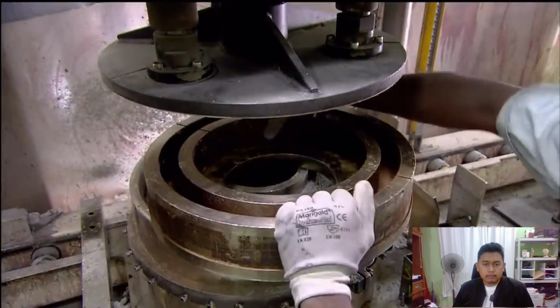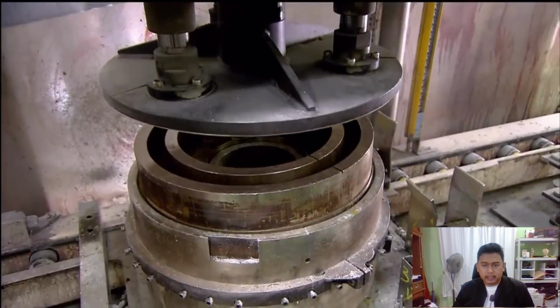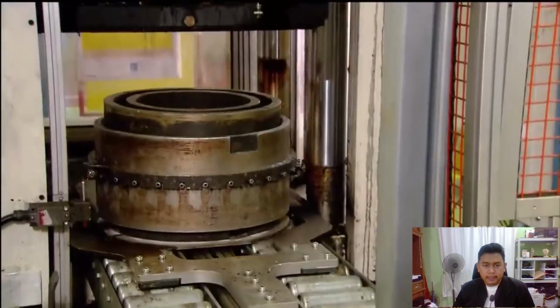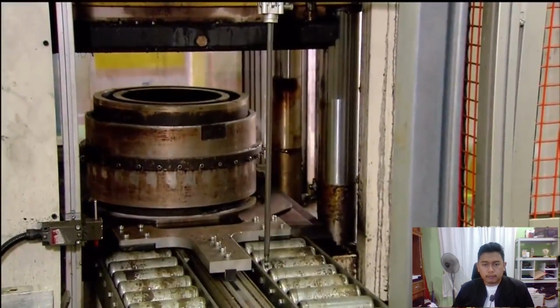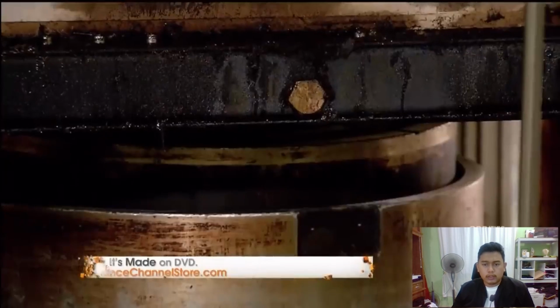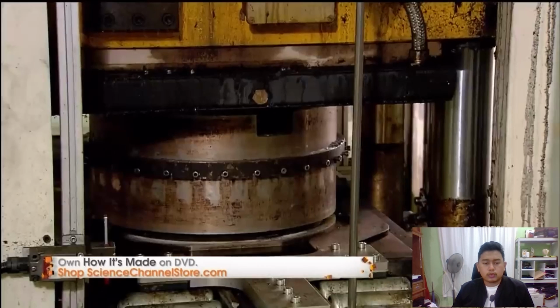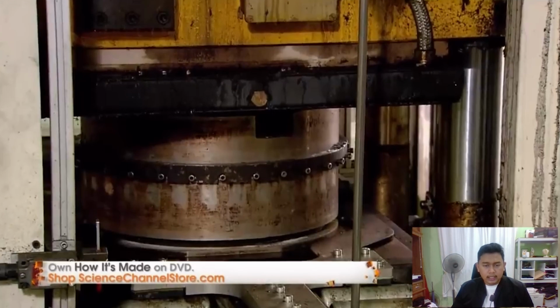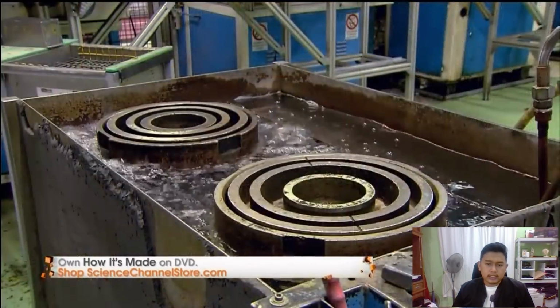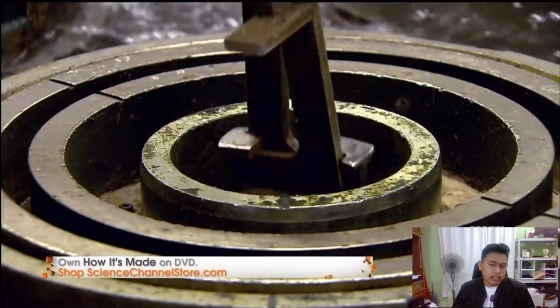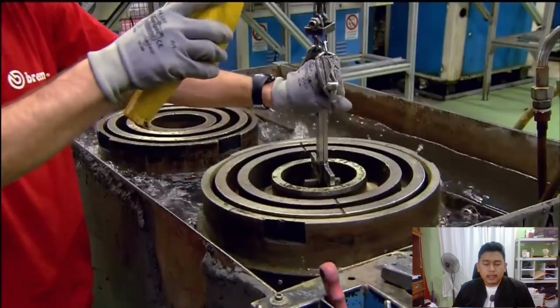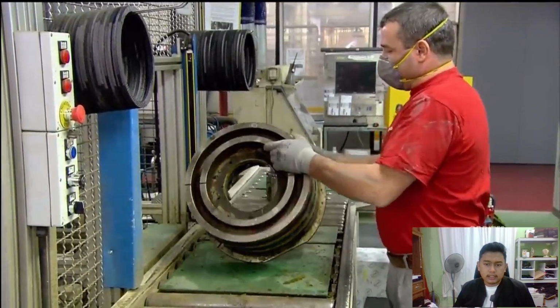And after that, the mold is closed and pressed lightly to compact the fill before entering a larger press, which will apply 20 tons of pressure, and at the same time the mold will undergo a heat treatment up to 204 degrees Celsius. This particular step will transform the resin powder into the plastics and compacts the carbon fiber, and then the mold is cooled until it is ready for extraction process. And before extracting the disc, the mold will be submerged in water for 5 to 8 minutes to ensure that the disc is completely cooled down, which will enable the workers to pull out the core.